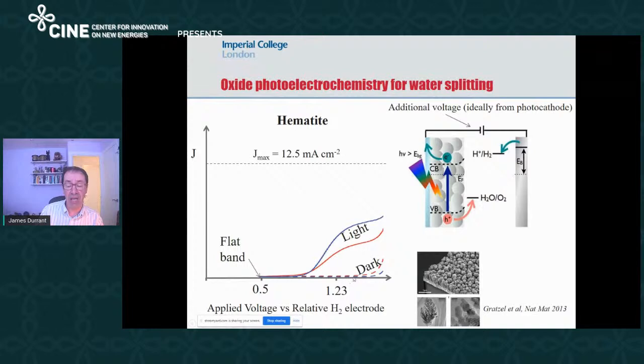And in the dark, you have to apply a large overpotential to drive water oxidation on hematite. In the light, you have to apply much less potential. So this, if you like, is photo-assisted electrolysis of water. And you can see there's a turn-on curve here, which corresponds to the turn-on of water oxidation at a certain